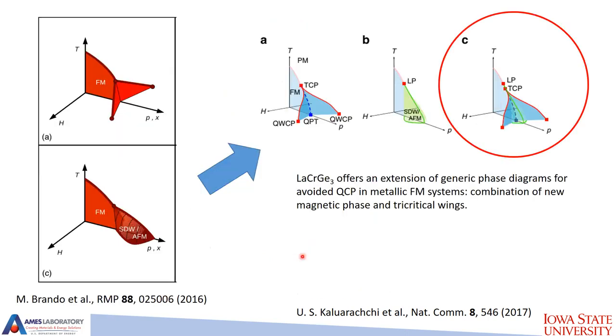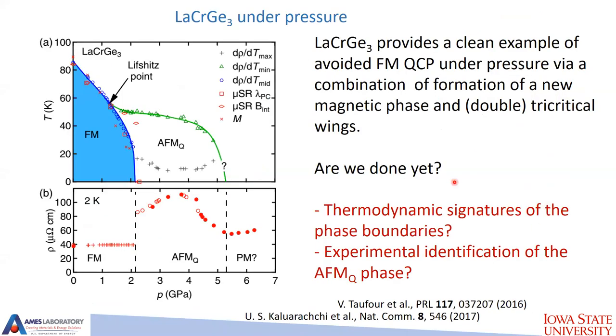So what is new in the studies of LaCrGe3 so far is that it's an extension of generic phase diagrams for avoided quantum critical points in metallic ferromagnetic systems. Not only do we have a ferromagnetic phase that becomes, as we thought at the time, an anti-ferromagnet, but we also have wings. Interesting. Let's go a little bit further. As a result of these two publications, we can say that this material provides a very clean example of an avoided ferromagnetic quantum critical point under pressure. It gives a novel combination of magnetic phase and tricritical wings.